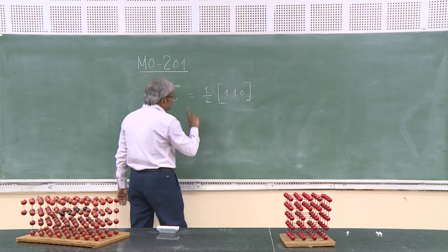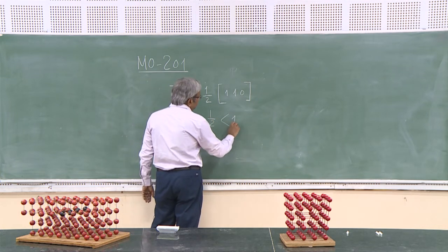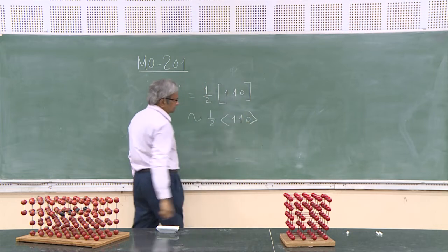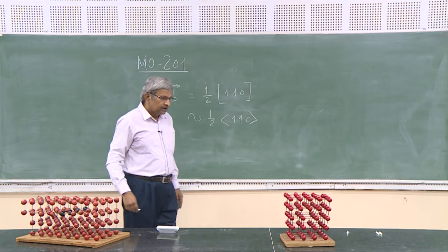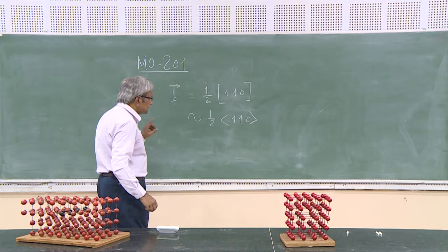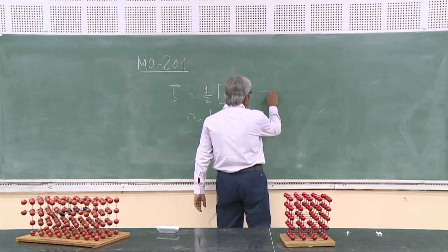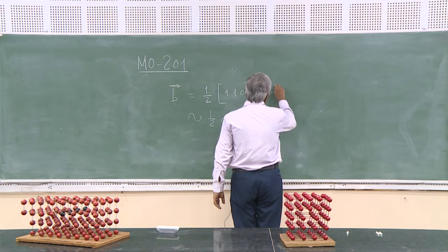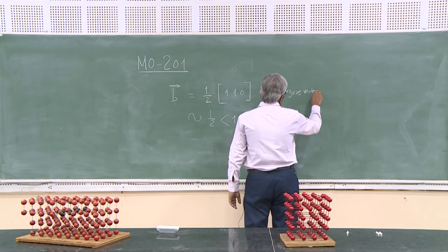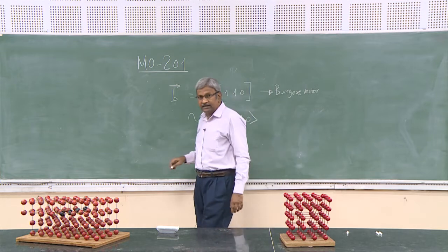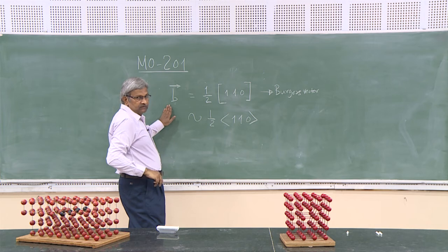In fact, to write the dislocation Burgers vector type, you should write all permutations of 110 type, which is going to be the Burgers vector of a dislocation in a CCP structure. However, as I have shown you in the class, this is the Burgers vector of a perfect dislocation.